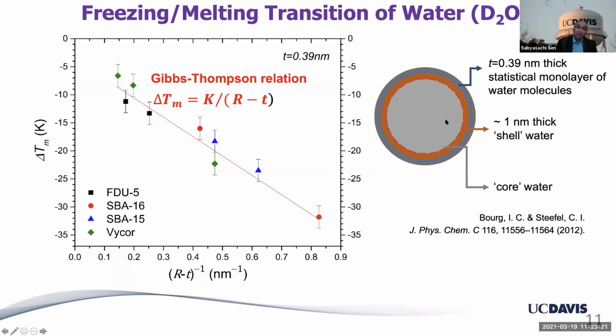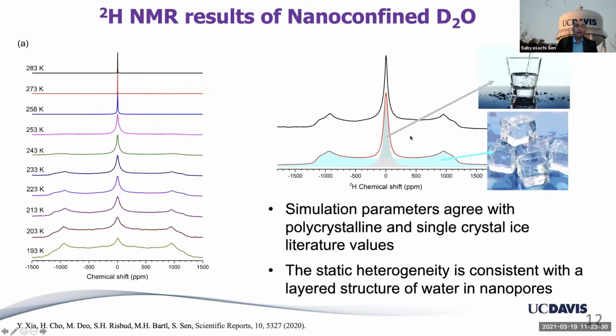So in order to see those things, one now needs to do spectroscopy to see, are there structural signatures of those kinds of water in there. So these are our deuterium NMR spectra in one of the confined media. They all look pretty much the same in terms of their behavior with temperature. So here is the lowest temperature spectrum we collected at 193 Kelvin all the way to 283 Kelvin, which is significantly above the melting point of D2O.